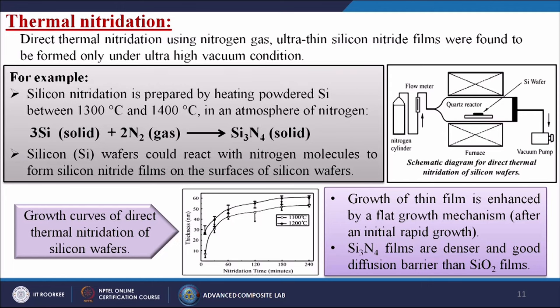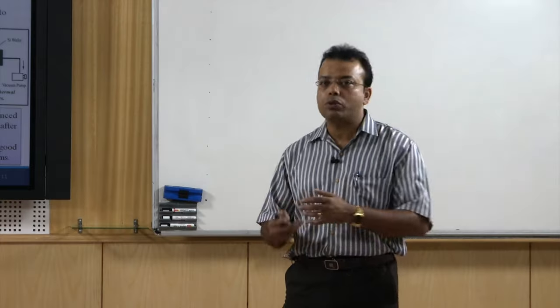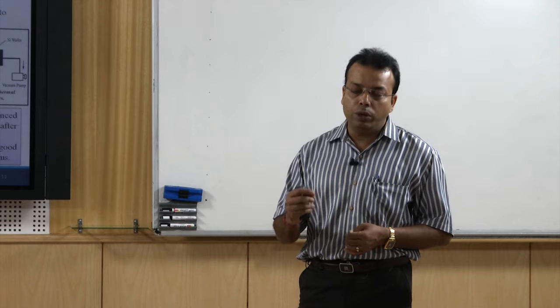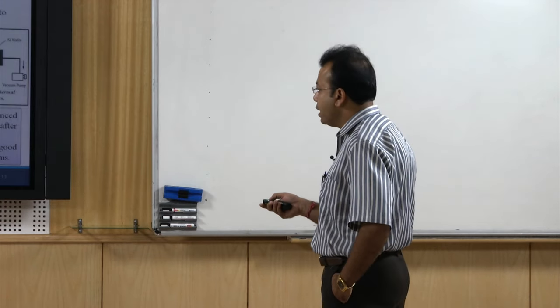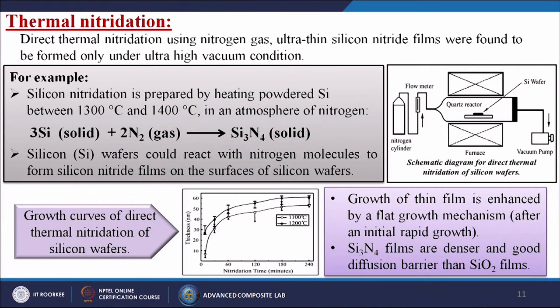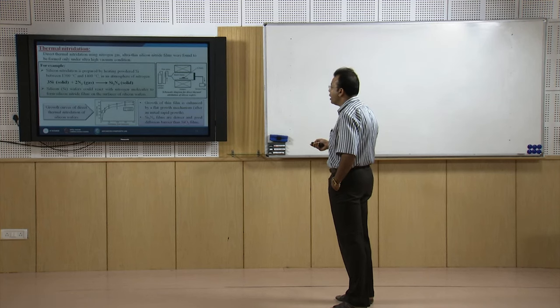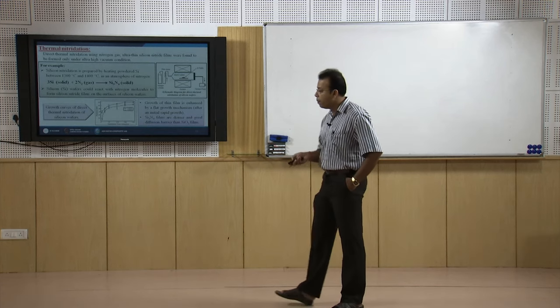This is the growth curve of the direct thermal nitridation of silicon wafers. If we increase the nitridation time in minutes, we can see that the thickness also increases. Here we have seen how growth takes place at two temperatures: one is 1100 degree centigrade and the other is 1200 degree centigrade. Growth of thin films is enhanced by a flat growth mechanism after an initial rapid growth. So if we run the experiment for a longer time, the thickness of the coating will increase. And silicon nitride films are denser and better diffusion barriers than silicon oxide films. This is the added advantage of thermal nitridation over the thermal oxidation process.